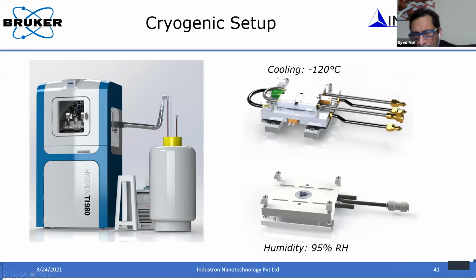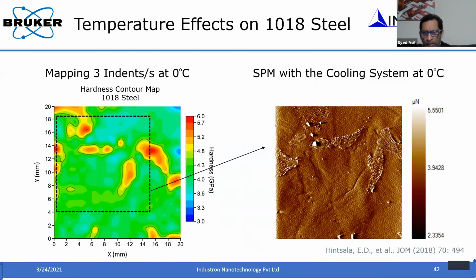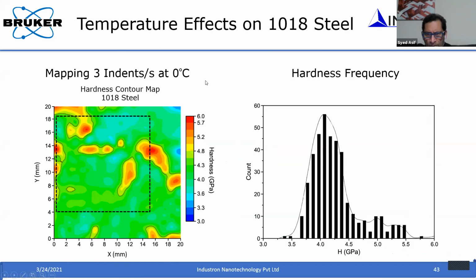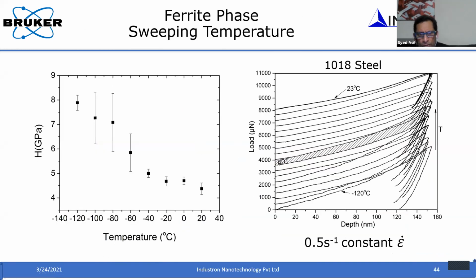Now, I mentioned that you can also do it at cryogenic temperature by passing cold nitrogen gas into the chamber in the same setup, and then you can cool it down to minus 120 degrees C. And this is for a steel sample, and you can see in the in situ SPM imaging the pearlite colonies as well as the ferrites. And with respect to indentation hardness mapping, you can compare that now even at 0 degrees centigrade. Okay. So I'm going to go and show this particular result.